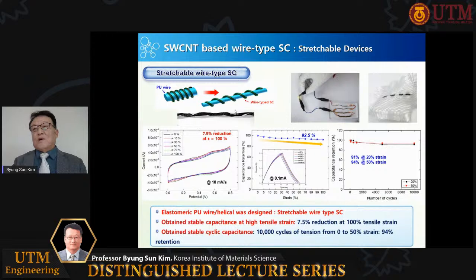Elastomer polyurethane wire and helical wire type supercapacitor was designed as shown on top left with stretchable wire type supercapacitor. After removing the polyurethane wire, stable capacitance at high tensile strain was obtained with 7.5% reduction at 100% tensile strain. Stable cyclic capacitance was obtained with 10,000 cycles of tension from 0 to 50% strain and 94% retention.